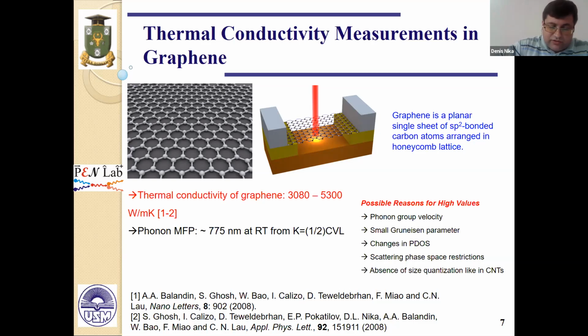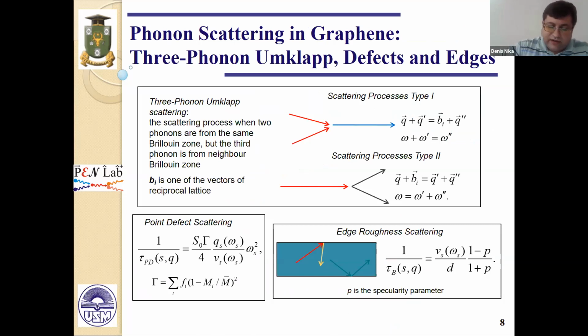Well-known 3-dimensional models of heat conduction were unsuitable for graphene due to the 2-dimensional nature of its phonons. Up to now, many accurate theoretical models were developed based on the kinetic Boltzmann transport equation or on classical or non-equilibrium molecular dynamics simulations. One of the first models explaining ultra-high values of thermal conductivity in graphene employed the valence force field model of lattice vibrations for description of phonon modes and the Boltzmann transport equation for calculation of thermal conductivity, taking into account all major phonon scattering processes in graphene: three-phonon Umklapp scattering, point defect scattering, and edge roughness scattering.